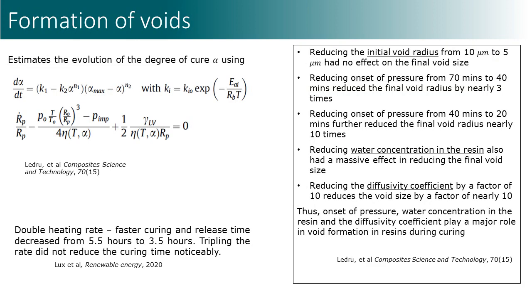Where do these voids come from? In order to analyze the formation of voids, we developed a code on the basis of the kinetic model of curing developed by Ledru and colleagues. Here, we see an overview of different mechanisms influencing the void formation in cured adhesives. Among different techniques, one should reduce water concentration in the resin, the diffusivity coefficient, and vary the pressure regime. Further studies of the ultraviolet curing effect, based on this approach, are underway.